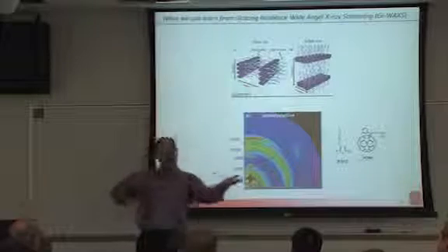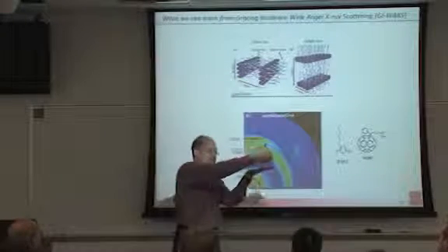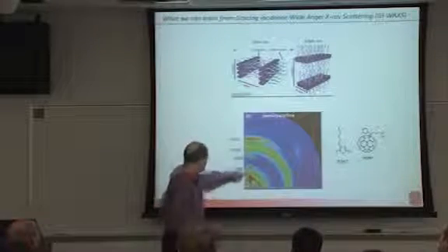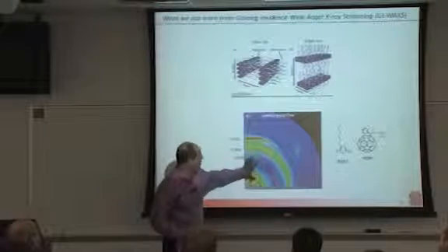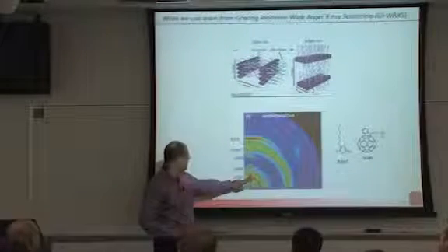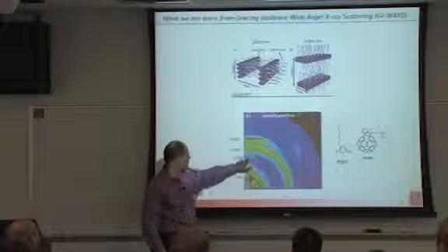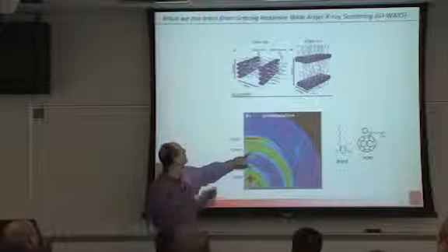Basically in grazing incidence, you come in at grazing incidence to your sample, you have a 2D detector, that is what you see, so I scatter off the sample, and then you can see a bunch of peaks here, and they're not circles, okay? You look at that, so this would be P3HT, the 100, 200, 300 reflections of the lamellar spacing, okay?